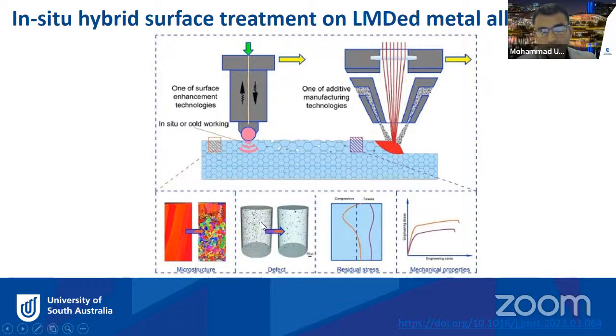Generally after the metal deposition, you can see the material is quite porous, but after the cold surface treatment, like a ball burnishing treatment, you can see here the porosity has been reduced, and also you can reverse the tensile stress into compressive stress. Compressive stress is generally beneficial for the fatigue life, and it has also improved some of the engineering properties like the yield strength and Young's modulus, and so on. So in situ hybrid surface treatment is growing, and it is quite popular.